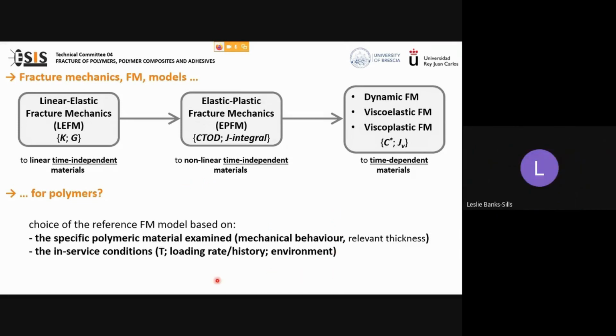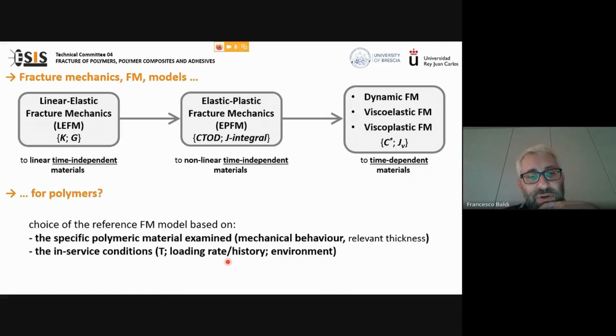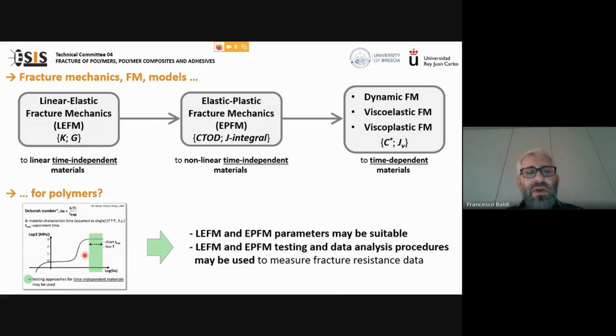Okay, thank you. Good. The in-service condition, therefore the temperature, the loading history, and also the environment where the material will work when in service. Now, if I consider the amorphous materials examined in two previous slides, and I consider the green region here at high levels of Deborah number, in this region I might try to apply the linear elastic fracture mechanics and the elastic plastic fracture mechanics approaches developed for time-independent materials. Therefore, the fracture parameters developed within linear elastic fracture mechanics and elastic plastic fracture mechanics might be suitable.